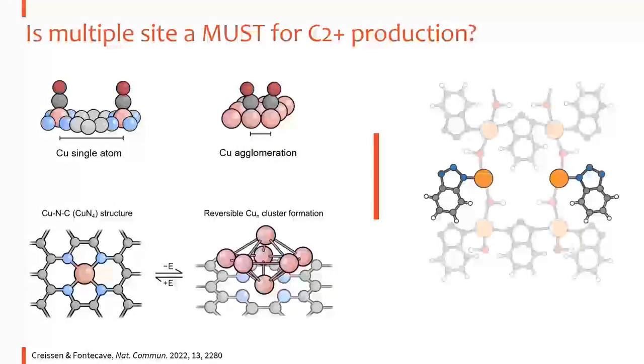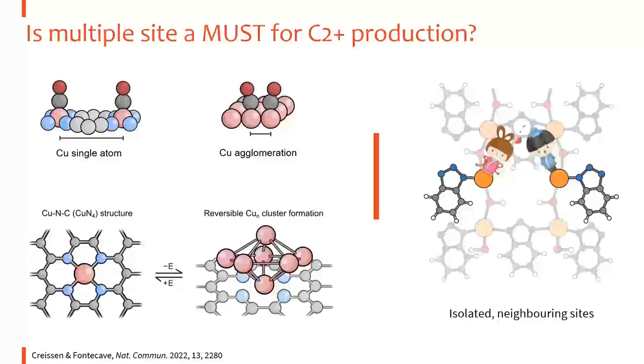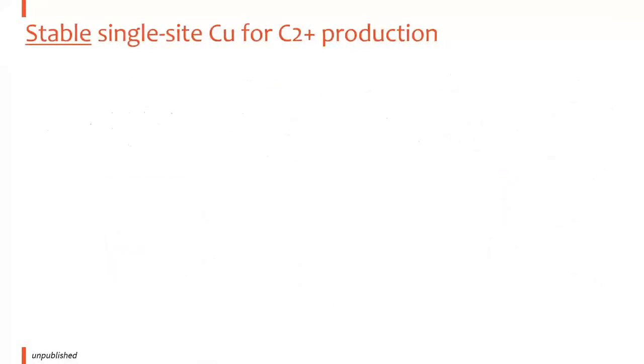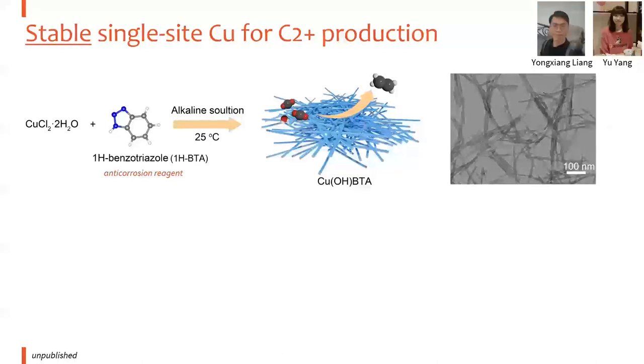So we are wondering if we can get single-site copper, that means even under operating conditions, the single-site copper does not aggregate into copper nanoclusters, while even if they are single atoms, they can promote C2 product. That means the CO intermediates on the surface of two isolated copper sites can couple together. So we need to create isolated while neighboring sites to enable two CO intermediates to couple together. So we set out to try to find that material.